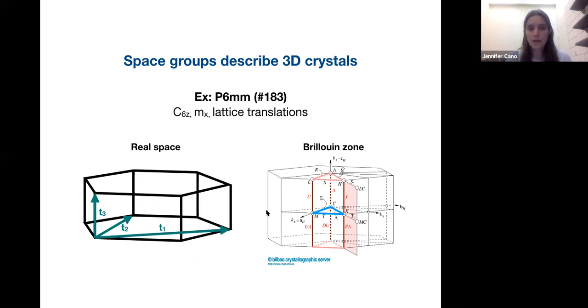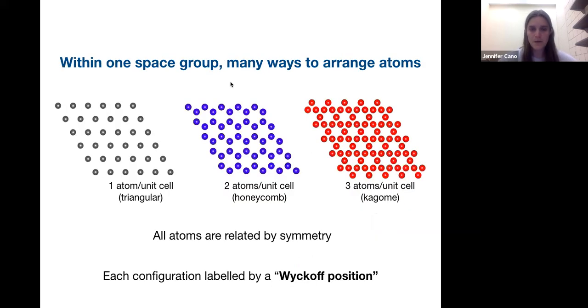The first thing we need to know is that the symmetry groups of 3D crystals are space groups. So a space group consists of some set of point group operations like rotations, mirrors, and then also some lattice translations. And these are the lattice translations that build up a 3D crystal from these point group operations. And in addition, of course, each of the space groups has a Brillouin zone, which tells us about the Fourier transform of this lattice. So symmetries in 3D are classified by space groups, but within one space group, the space group doesn't specify how to uniquely arrange atoms. There's many different atomic configurations that satisfy the symmetries of the space group.